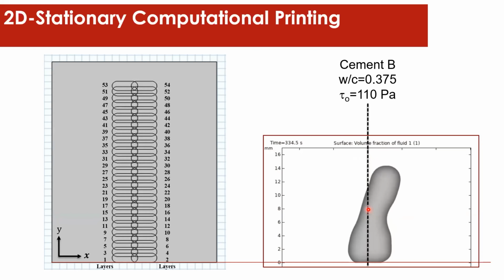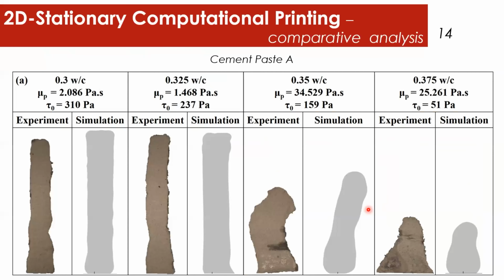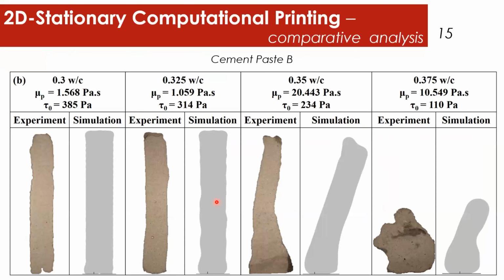So here is the collapse of the wall. Here you see the comparison of the cut cross section of the actual printed object and the computationally printed object, which are in good agreement for cement paste A, as well as for cement paste B. At high water to cement ratio, the computationally printed object also predicted the collapse or failure similar to the actual printed object.